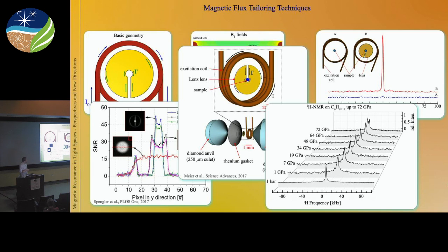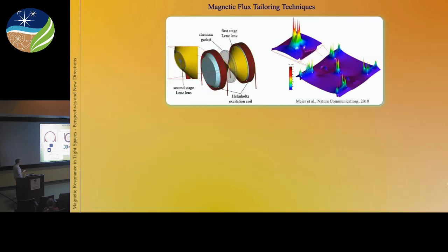After we were able to publish these results in Science Advances at the end of 2017, we of course thought that it might be even better to combine physical vapor deposition techniques with FIB milling. And this is exactly what we did. So we took 2 diamonds having symmetric culets, covered them completely in copper of approximately 1 micron. Then we put these diamonds into a FIB and cut out shapes like that. We have 2 lenses per diamond,